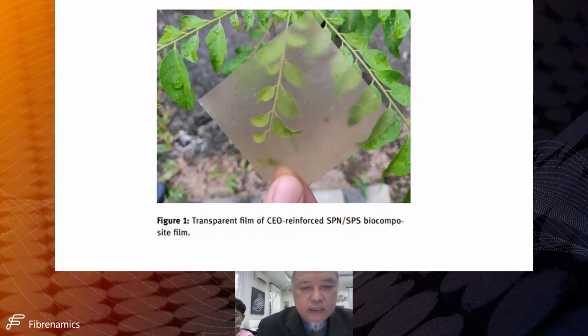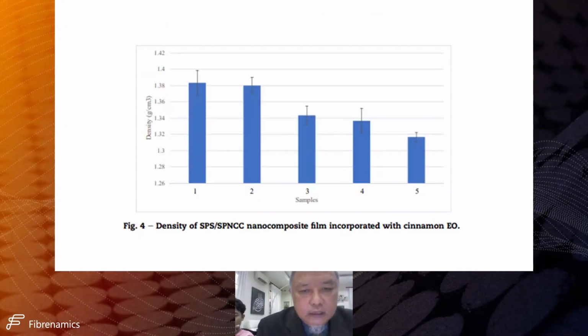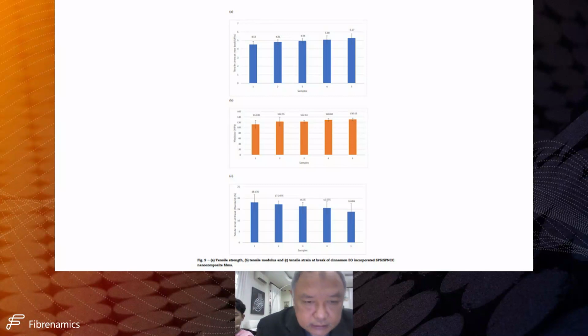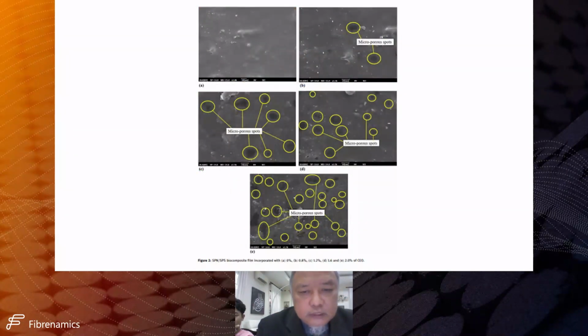And this is one of the transparent films from the sugar palm nanocellulose sugar palm starch biocomposite, and the density when we include the cinnamon essential oil tends to decrease. But the tensile strength is not much different in terms of the strength properties.